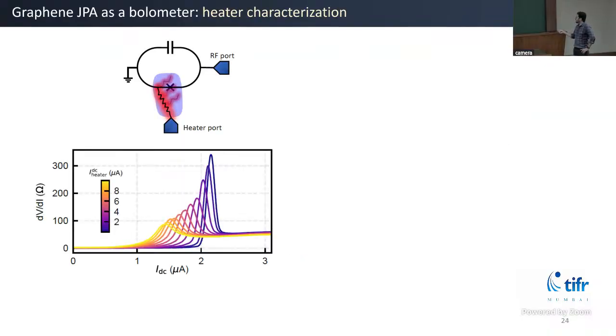Again, in the experiment, we first characterize this device in DC to check whether it is working properly. Here I'm showing you differential resistance as a function of bias current, and in the color, what I'm changing is the heating. When there is no heating, you are seeing a large critical current, 2 microamps. Now, as a function of heating, your critical current is reducing. That is expected because you are changing the temperature of the Josephson junction. Also, this peak broadens, an indication of heating here.